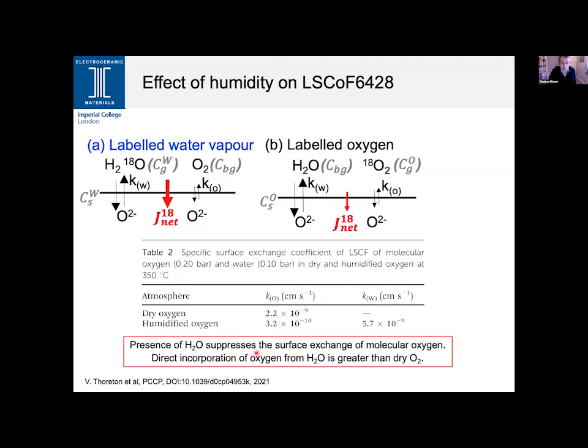Their observation is that the water again suppresses the surface exchange of the molecular oxygen, but the direct incorporation from the water molecule was greater than the dry oxygen species at these temperatures. So the effect of humidity on the surface exchange and diffusion parameters in these perovskites is really quite profound and quite significant, and therefore is certainly a parameter that we should be taking into account when we're considering the materials for application in devices. And this work of Vincent's has just been published. The DOI is there in PCCP.